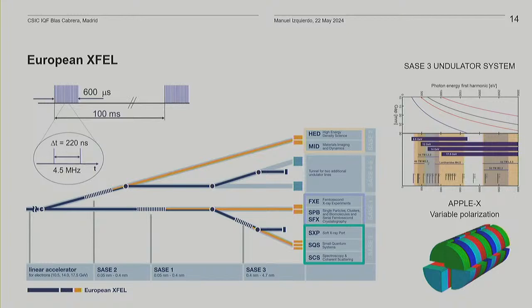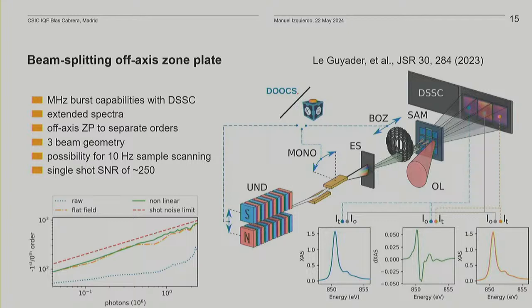So then X-FELs became available in the meantime, and in particular SASE-3 with an availability of between 300 electron volts and 3 kilo electron volts. And then we decided to investigate it again. But the problem of free electron lasers is that all pulses are different in intensity and pulse energy, and for this we implemented a method at the SCS, which is the beam-split off-axis zone plate method.